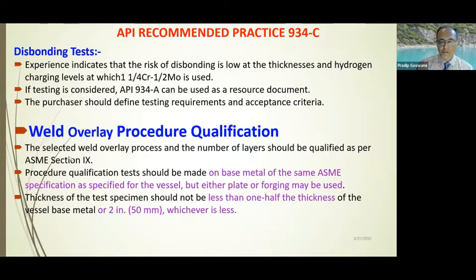Weld overlay procedure qualification: the selected weld overlay process and the number of layers should be qualified as per ASME Section 9. The procedure qualification test must be made on the base metal of the same ASME specification as specified for the vessel, which could be either plate or forging. So if it is SA-387 Grade 11, Class 1 or Class 2, it has to conform to the same specification, and that product form could be either plate or forging.